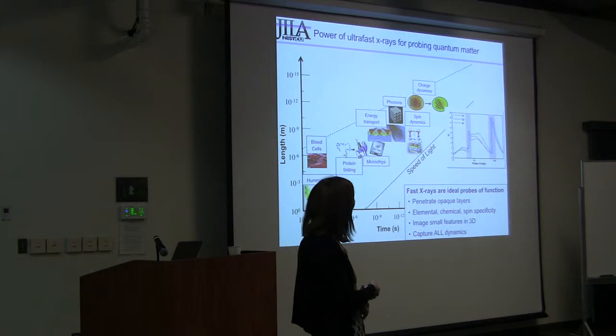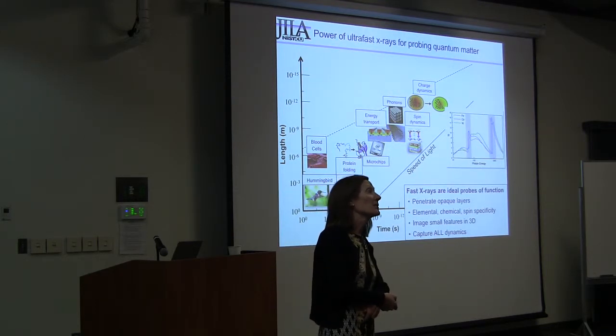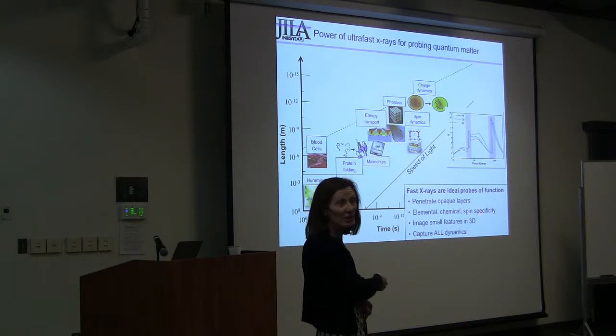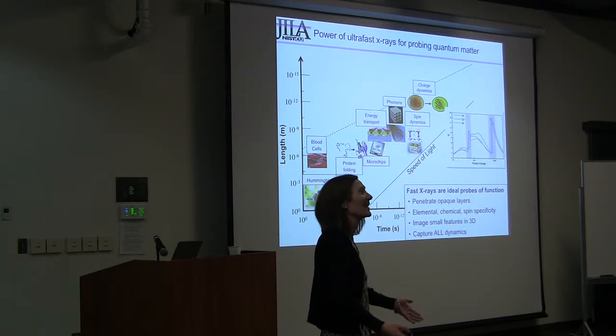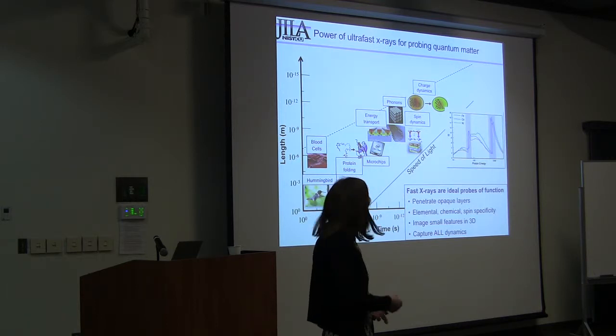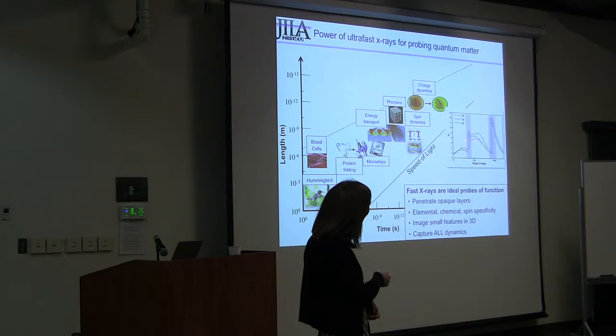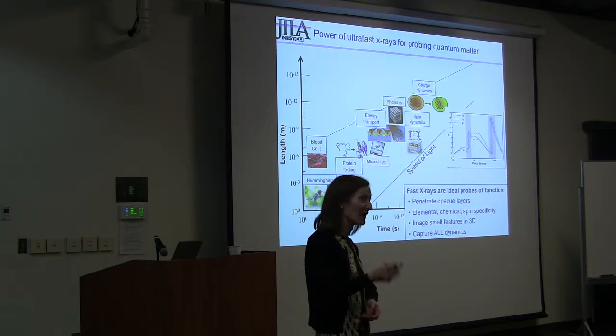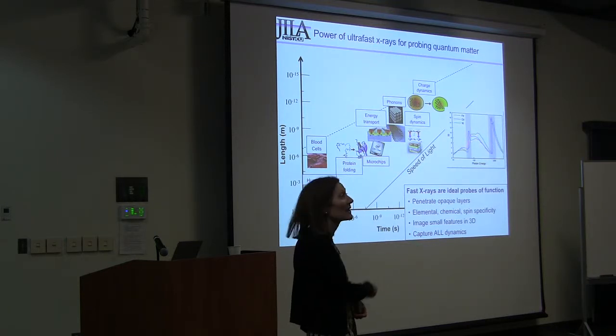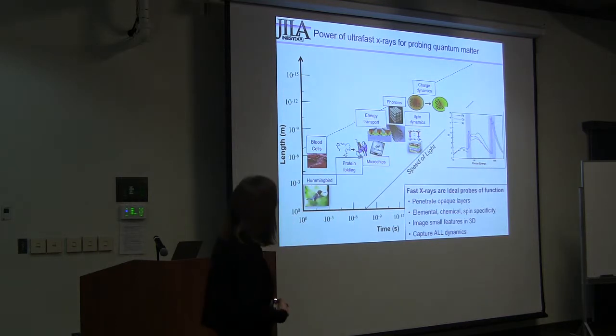And what X-rays do for you, which a visible ultrafast laser cannot, is it can penetrate through thick samples, like a magnetic material. It's not transparent to visible light. You have here the X-ray absorption edges of three magnetic materials, iron, cobalt, and nickel. They have these characteristic absorption edges, both in the extreme ultraviolet, around 50 eV, and those are the M shell absorption edges, and also in the soft X-ray, these are the L shell absorption edges, and there's nice magnetic contrast at either edge. And so currently we're doing all our work at these M shell absorption edges that are very easy to reach with high harmonics.